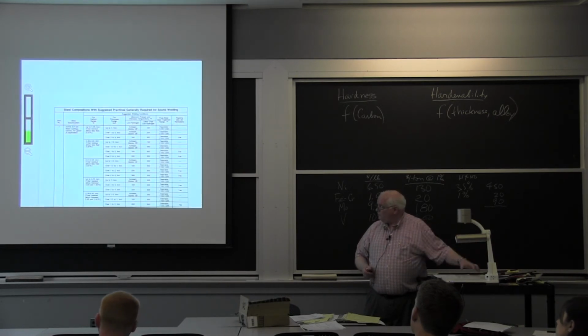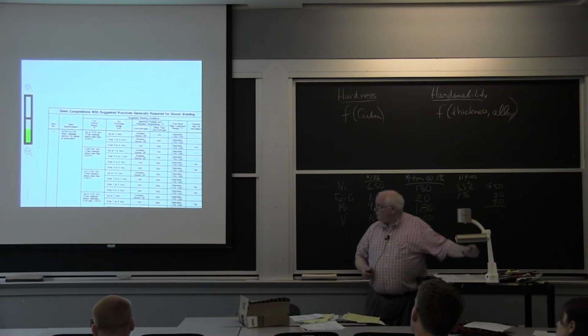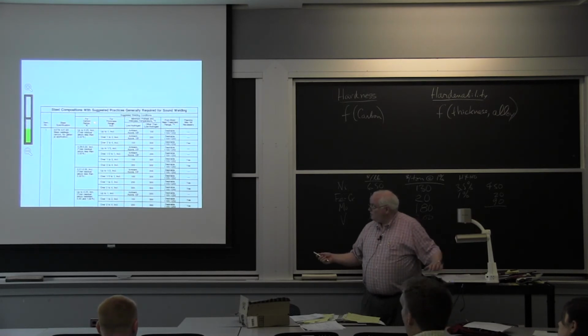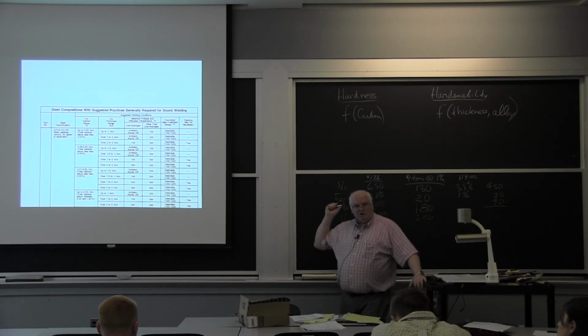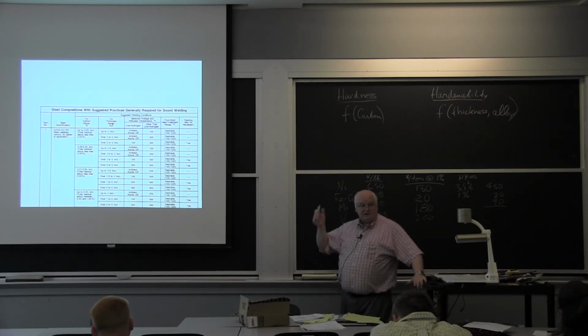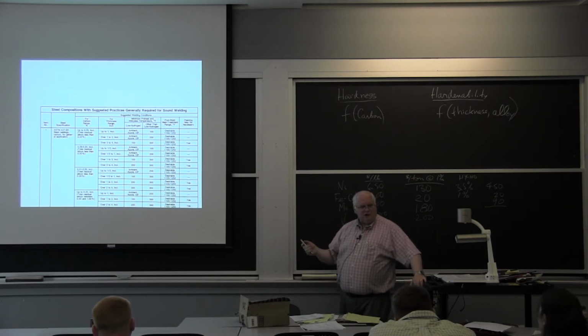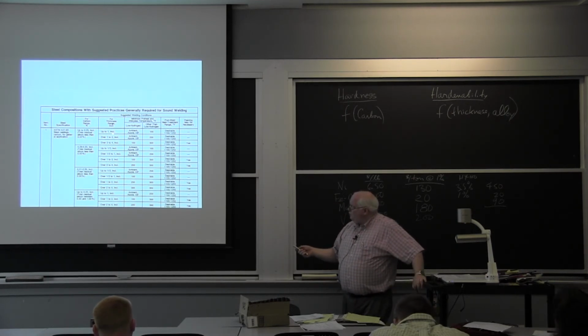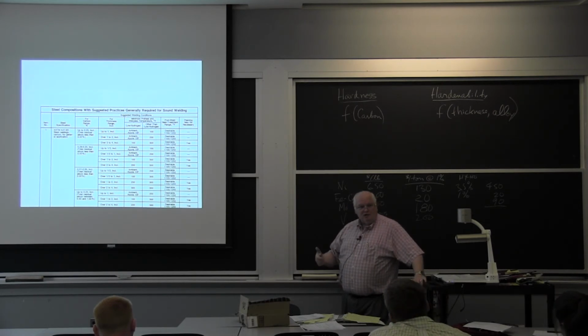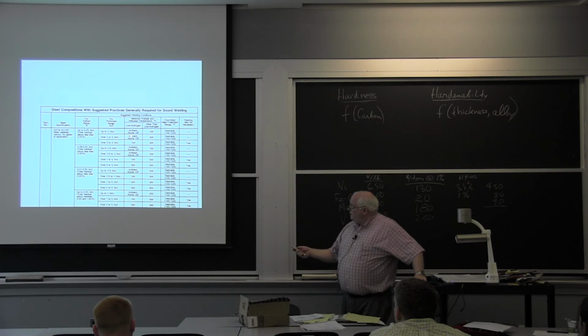Again, you know, being an expert is sometimes just knowing where to look, right? That's what I said before. So the first thing is the carbon range. That's your hardness. The next thing is the thickness, okay? This sort of fits together with what I just put up on the board, right? And the thickness range, they may break it up, because how fast it cools depends on how thick it is. You know, I'm putting the same size weld bead on, okay? Thicker, faster cooling. Then the minimum preheat or interpass temperature in degrees Fahrenheit, depending on what type of electrode, whether I'm using low hydrogen or other than low hydrogen, which means high hydrogen.